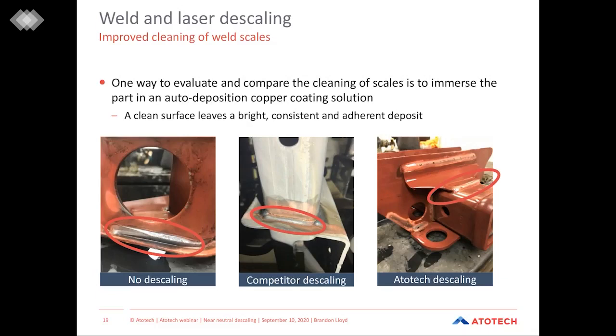And then lastly, the image on the right is Atotech descaling with Uniprep AC. And we can see that we have very good coverage. It leaves a bright and consistent deposit on the part and is completely adherent to the weld itself.